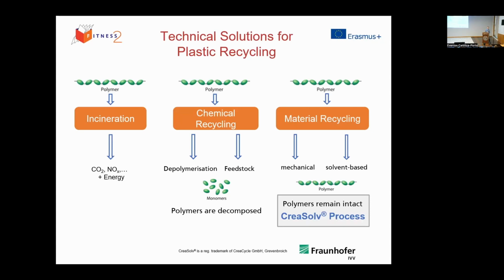And the most common one is currently the mechanical recycling, but this requires a high purity of the waste stream you want to recycle. We focus at our institute also on the solvent-based recycling. Here you physically dissolve the polymer from the mixture, and it also stays intact as in mechanical recycling. So the polymer chain itself remains untouched.